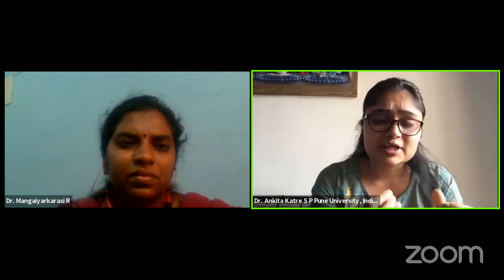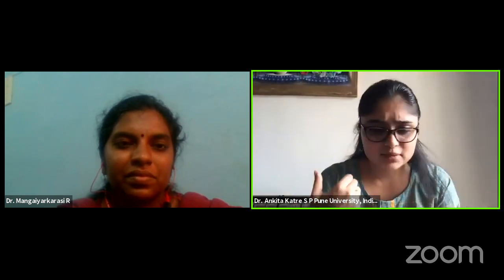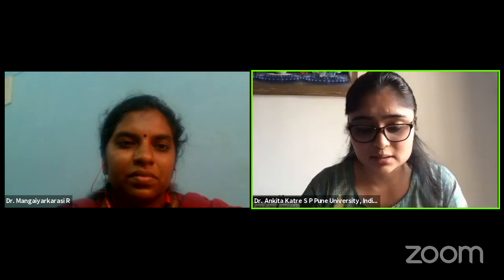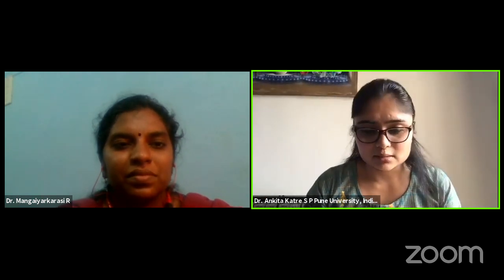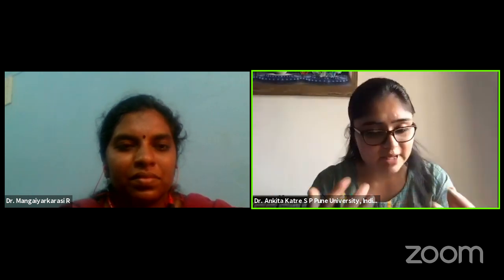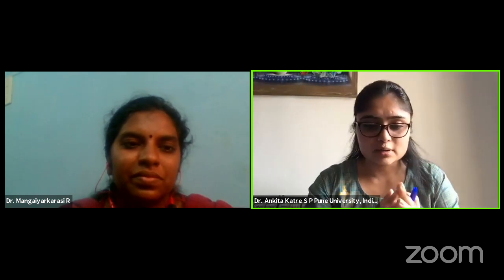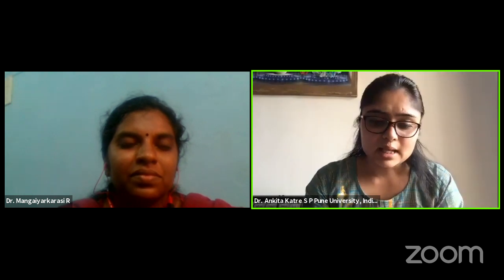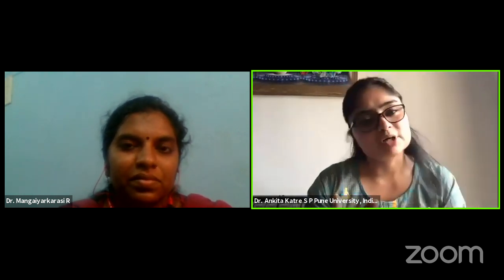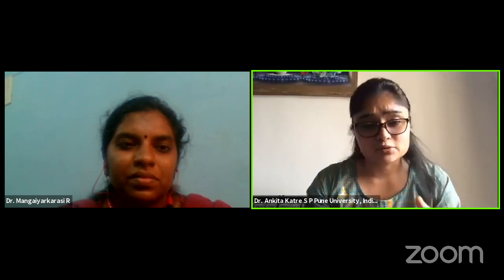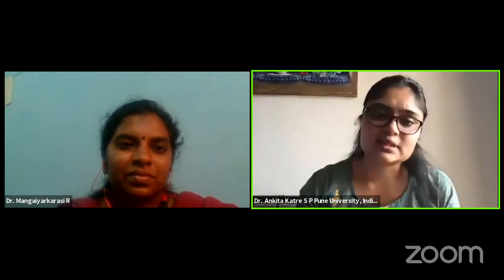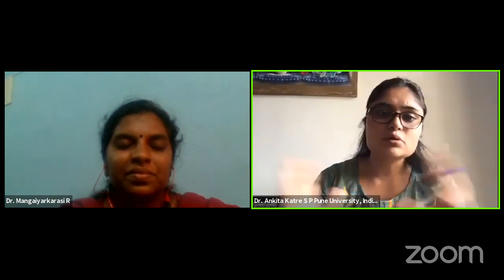With low, I mean basically in the range up to, depending on the material and the defect, maybe around 0.01% to 3 or 4%. The linear approximation could be okay. However, after that things start changing. If you have very high concentrations of defects, first it will be called an alloy. And with that alloy, the whole geometry of the structure could change, and it may not remain in the parent structure, and then it becomes a different structure. Or sometimes it could also happen that it will just phase separate, and we can get different phases as well. So with defect concentrations, all these things could happen, but here we are in the limits where the parent structure is not changing, and the distortions are not so much that the whole system would completely collapse.